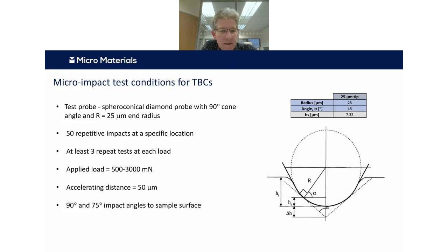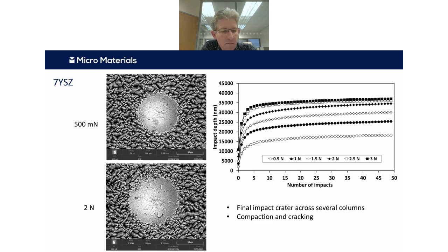So when we're looking at these test data, we think it's better to think of these as spheroconical probes rather than spherical probes if the impact depth is greater than that. Here on the left are a couple of example SEM images, and we can see some compaction and some cracking within the crater and also at the edge of the crater. There doesn't appear to be much obvious difference in mechanism across that load range. If you look at depth versus impacts, the trends are relatively smooth, so there are none of these abrupt material removal events like I showed you on the alumina example way back at the beginning.